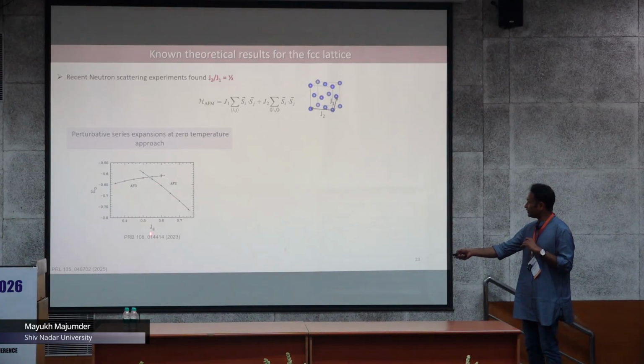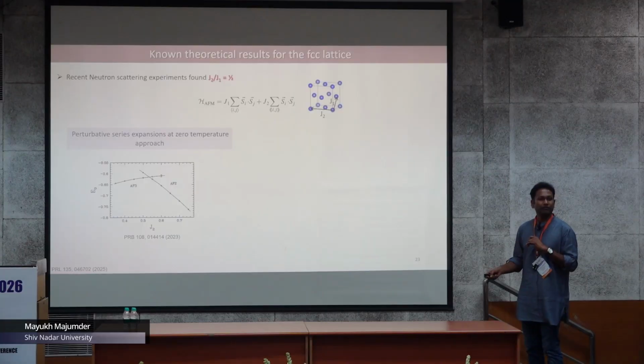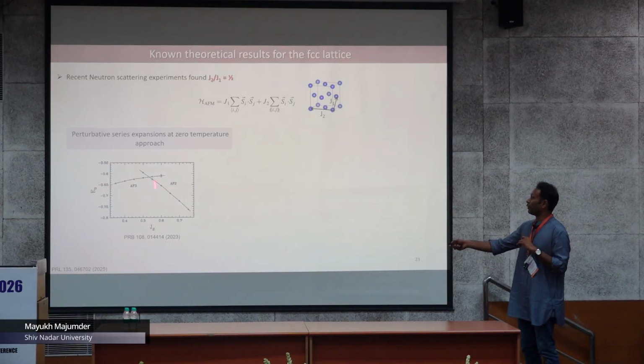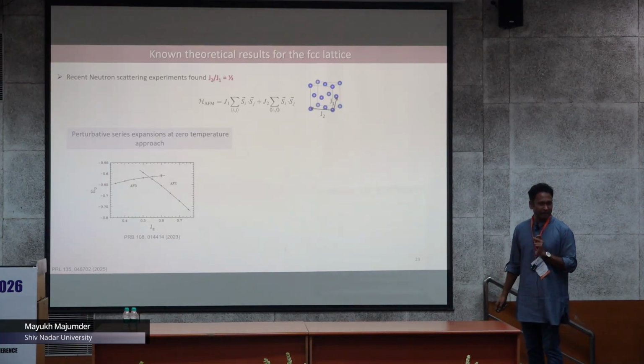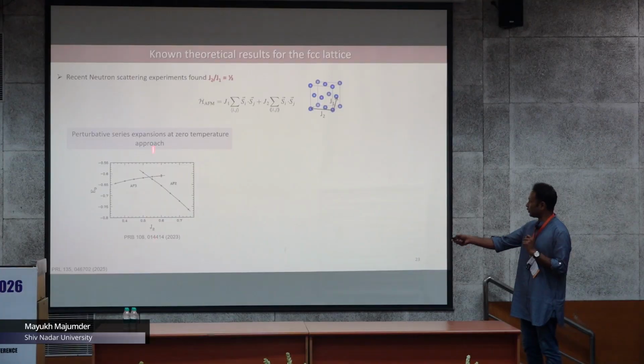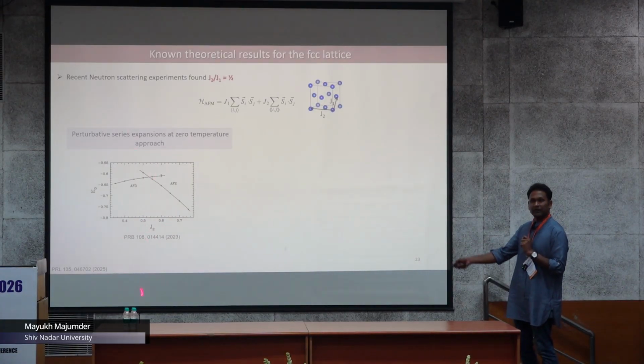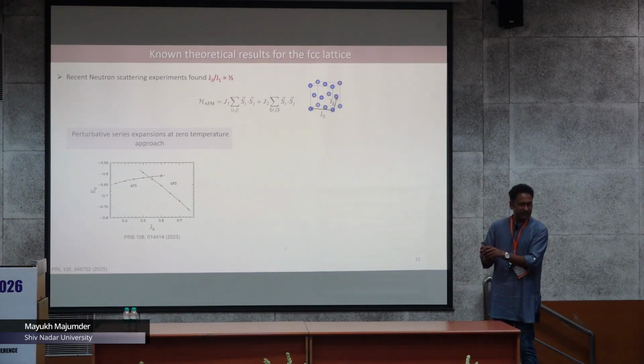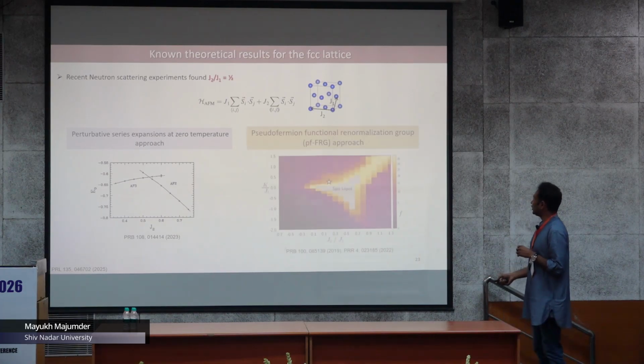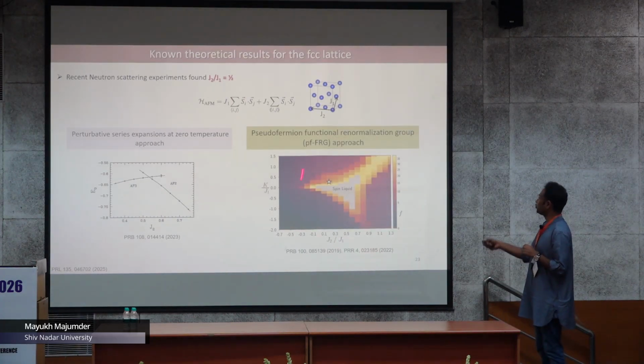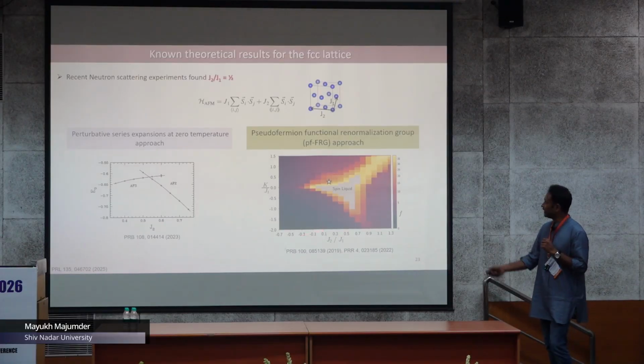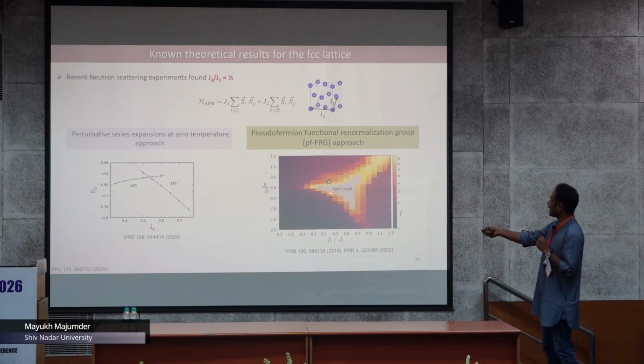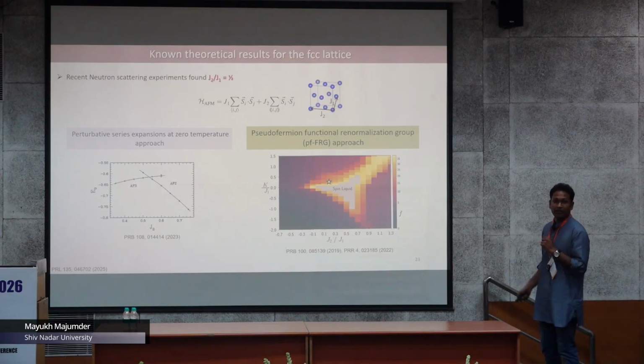They saw that around this J2 by J1 ratio of 0.5, there is a sort of boundary between two different types of antiferromagnetic states. So it is highly possible that around this regime there is a sort of degeneracy between these two states. And even more recently, both of these two papers, following this pseudo-fermion functional renormalization group approach, indeed saw that there is a possibility of having a spin liquid at J2 by J1 around 0.5.